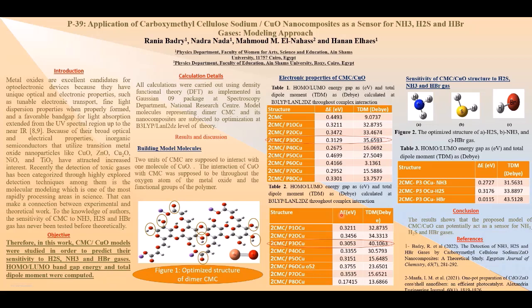By comparison, these two tables show that the most favorable interaction mechanism will be the one that occurs through the adsorption interaction, as it has the lowest HOMO-LUMO band gap energy, which means it is the most probable interaction to occur.